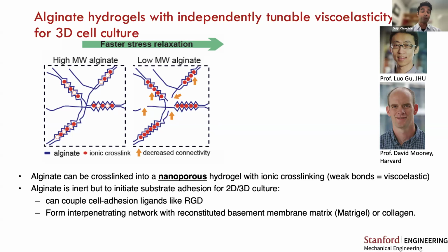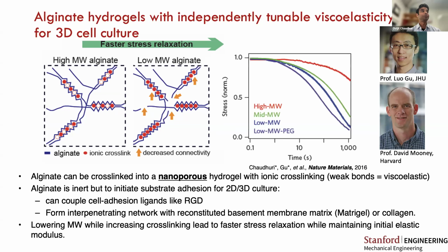Now, some other important features of alginate are that it's inert. So cells have no way of binding to alginate itself, and they can't degrade alginate, or at least mammalian cells can't degrade alginate using proteases. However, we can couple cell adhesion peptide motifs such as RGD to allow cells to bind to the alginate through integrins, or we can form interpenetrating networks with things like reconstituted basement membrane matrix or type 1 collagen to form a bioactive matrix.